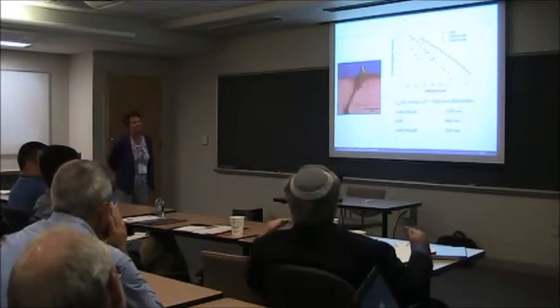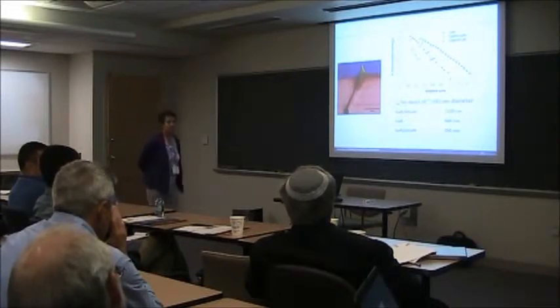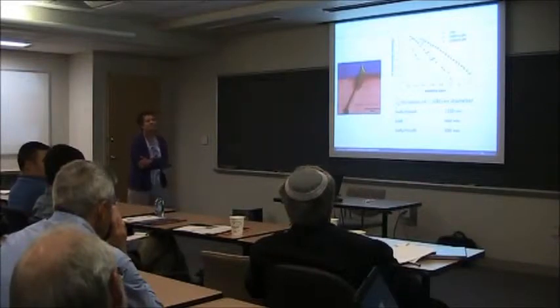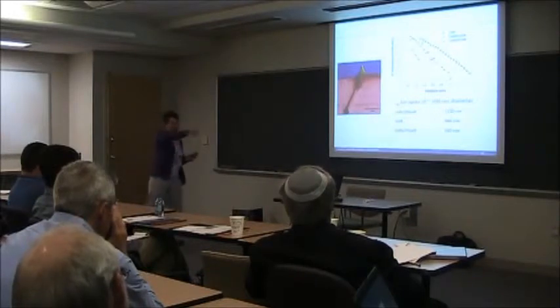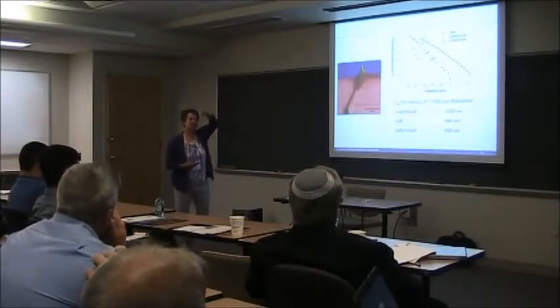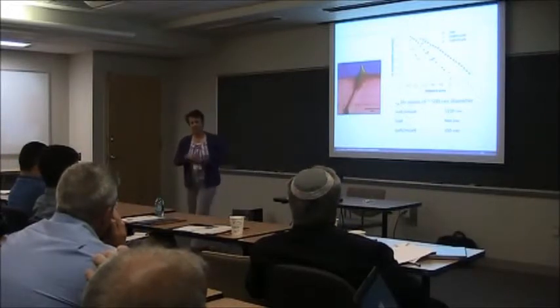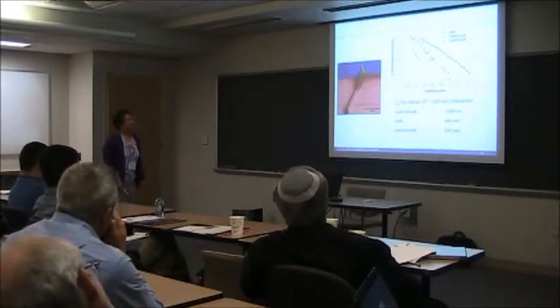Yes, but what happens is that a near-field optical probe has a very large angle of acceptance, so that the amount of light that's collected is biased to near the probe. So you're seeing mostly, I would say, 100 to 200 nanometers, depending on the size of the probe. These are about 200 nanometer diameter, maybe. And remember, these photons are coming straight up. They're not the ones that are propagating. Deeper ones could be, right. These are the ones that are recombining along the way. So it's like having multiple generation sources all down the wire. Right, that's true. I mean, you're correct that I've got this other light that's working its way, but hopefully that is of course. But that's not producing more electrons. No, that's just guiding photons. That's right. Yeah, absolutely.